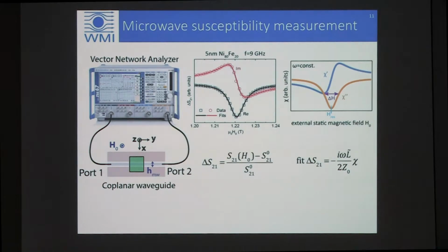So this is a quantitative agreement, and I want to point out that there's this inductance L, which is given by this expression. So this is fully quantitative, to the point that we don't really need a fit anymore. This is still a fit, but I can actually plot the theory, and it quantitatively matches the experimental data points rather well.